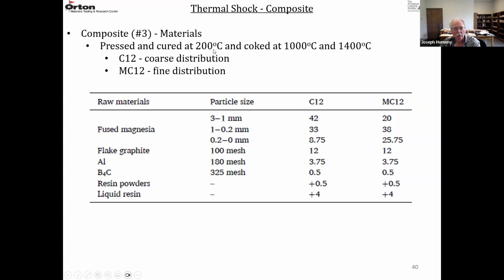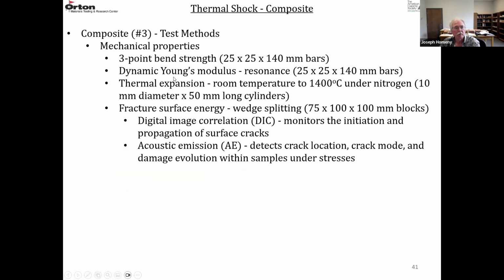So these powders were pressed. The resin was set at 200 degrees C, and these materials were coked to pyrolyze the resin at either 1,000 or 1,400 degrees C. So C12 is coarse, MC12 is finer. They used a 3-point bend strength, typical bend bar size, 25 by 25 by 140 millimeters. They measured Young's modulus by a resonance technique. Thermal expansion was measured up to 1,400 degrees C under nitrogen with these smaller cylinders, 10 millimeters in diameter by 50 millimeters long. And the fracture surface energy was by wedge splitting on the typical sample size.